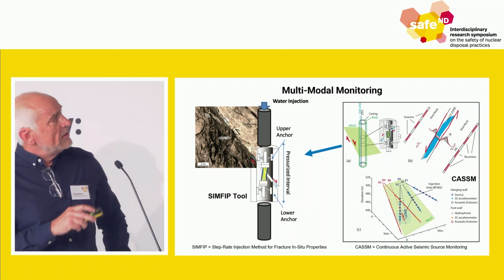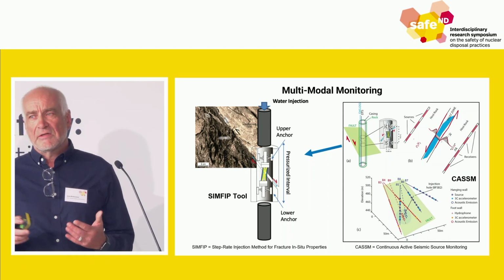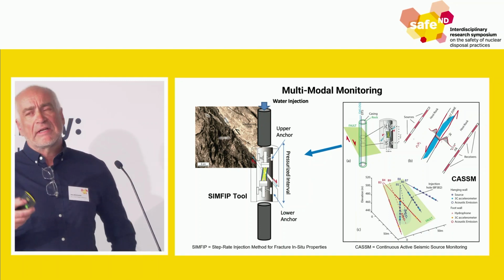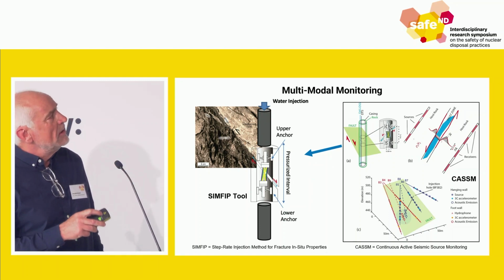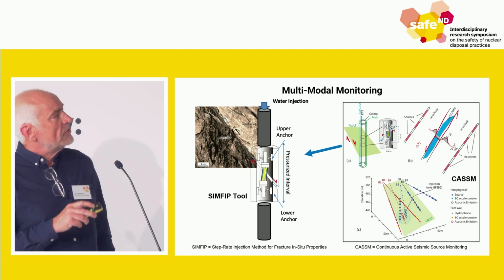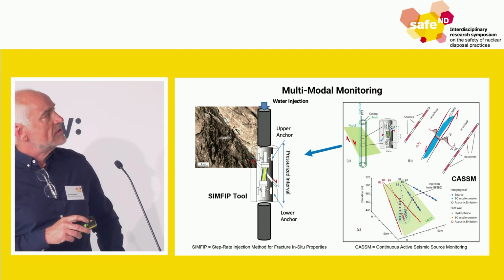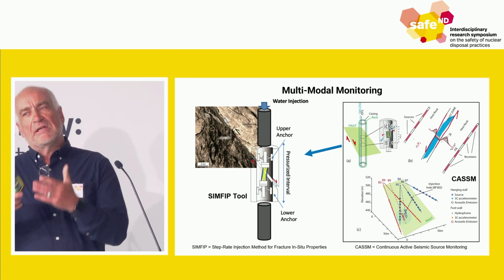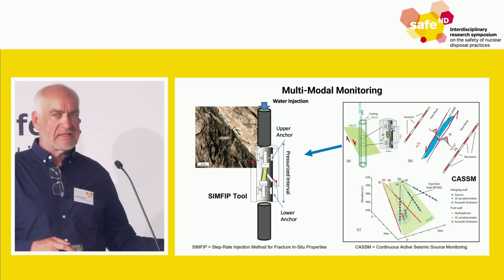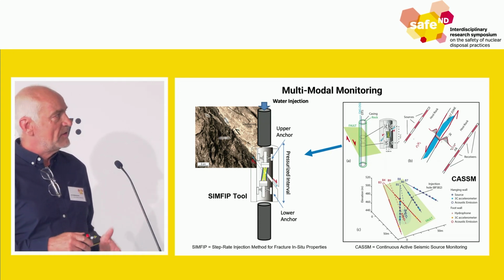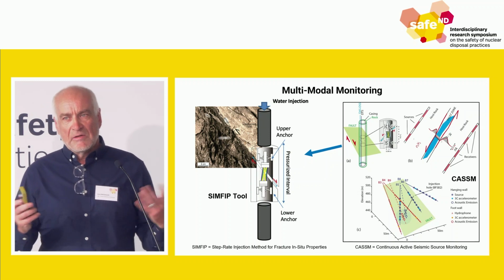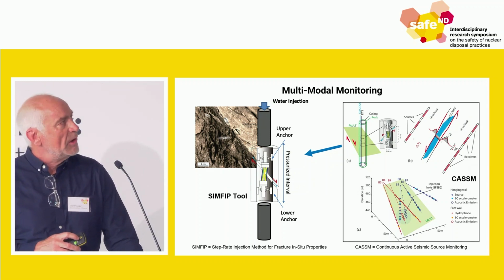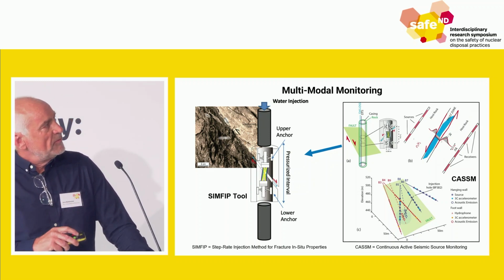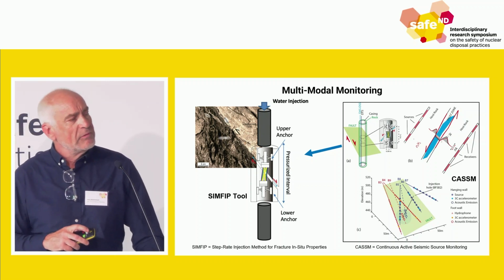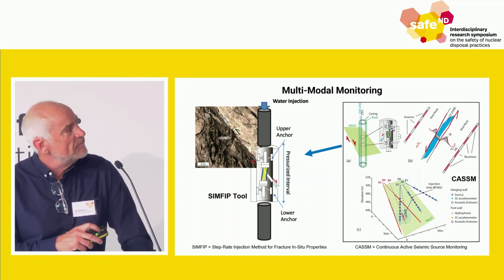So as you put that into this cross-cutting through the fault, you inject, and at the same time measure flow rate, which tells you something about permeability. You measure pressure, you measure the deformations, and you can use that both in an injection sense, or place it in a monitoring borehole and do this in passive mode. We used that in the first experimental series and in the second, larger test bed.